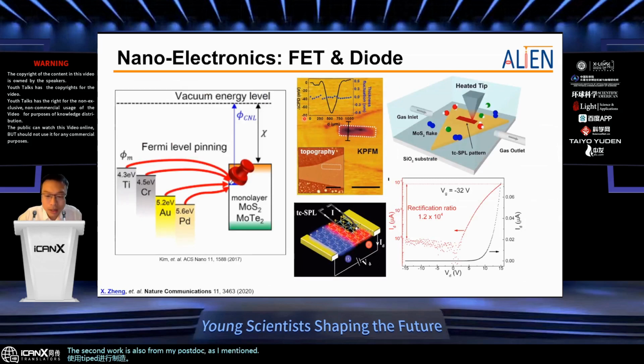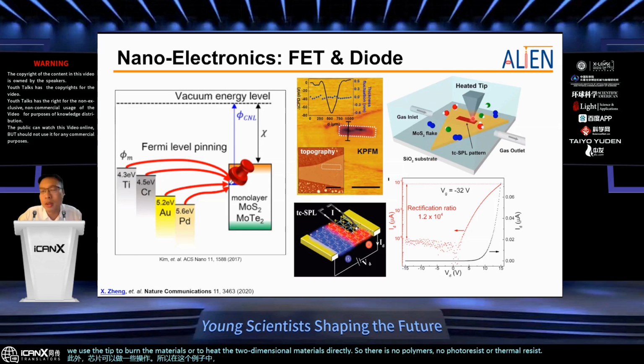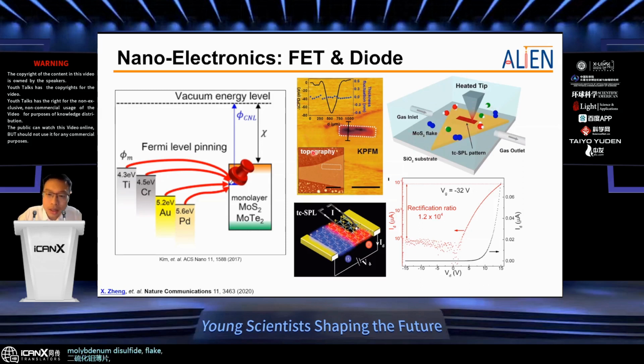As I mentioned, the tip can make nanofabrications, make patterns. Also, the tip can do some manipulations. So in this example, we use the tip to burn the materials, or to heat the two-dimensional materials directly. So there is no polymers, no photoresist or thermal resist. We use the tip to heat up to 300 Celsius, and we heat the molybdenum disulfide flake directly. As you can see in the topography images, there is no scratching, or we keep it to minimal scratching on the TMDC flake.